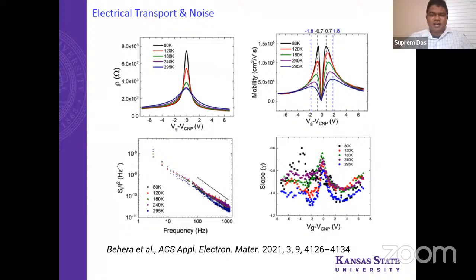So it's very high compared to silicon. Now with temperature, as you can see at 80 K, we got almost 140,000 to 150,000 mobility. So very, very high mobility. That's how we confirm that our devices have ultra high mobility. So we ensure that before measuring the noise.